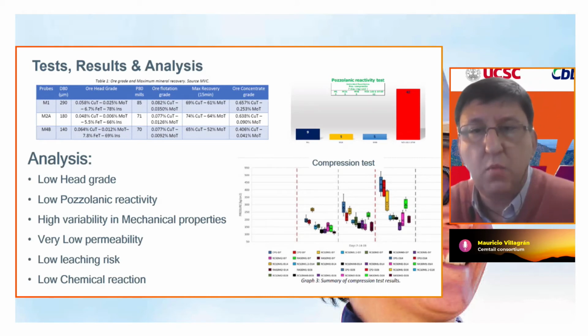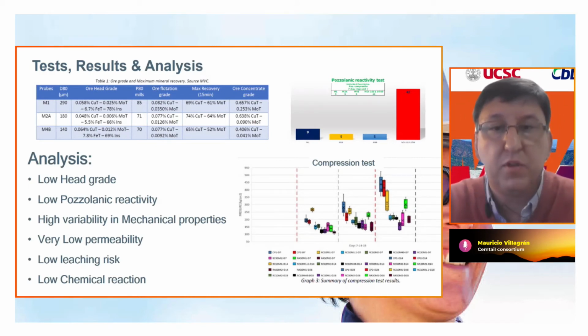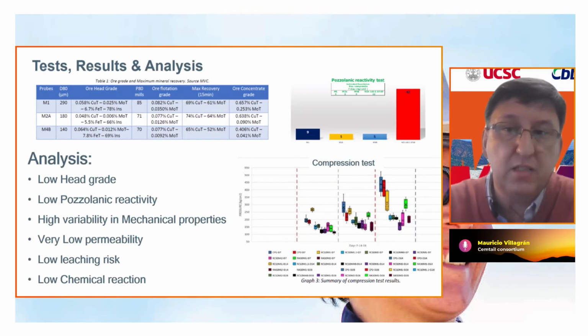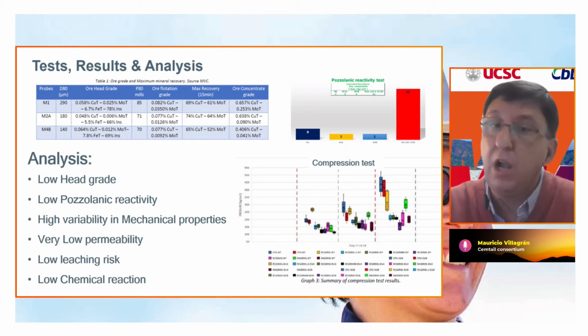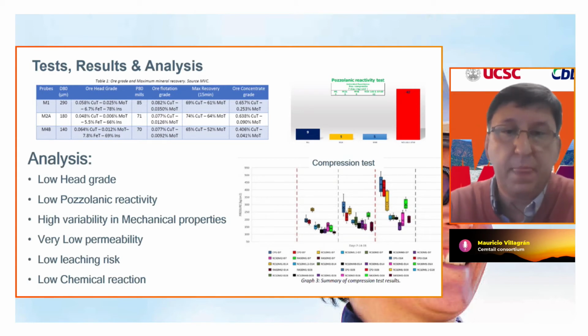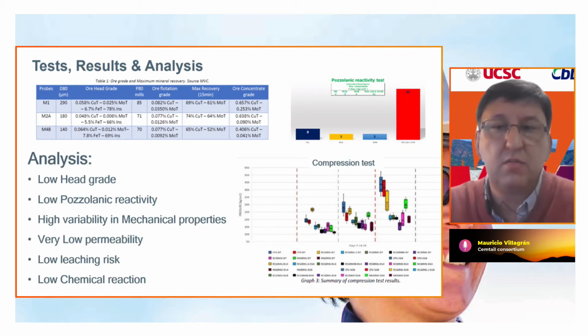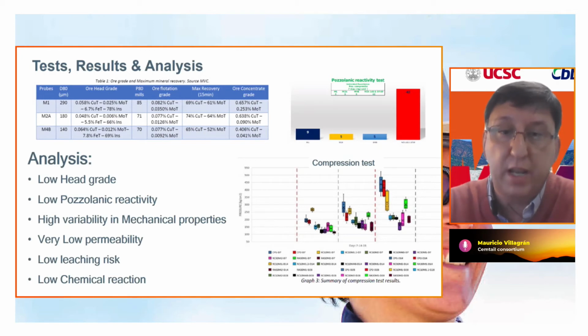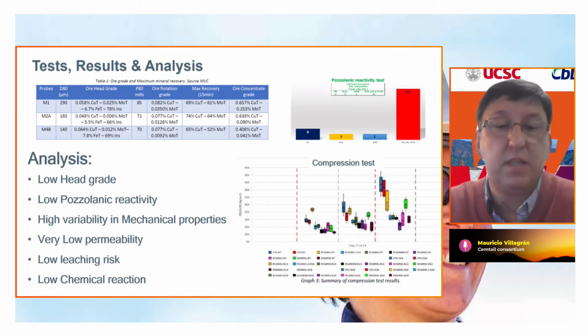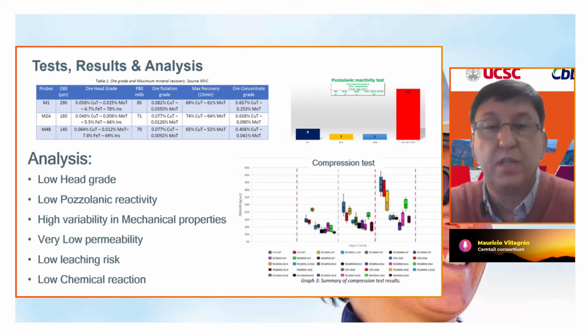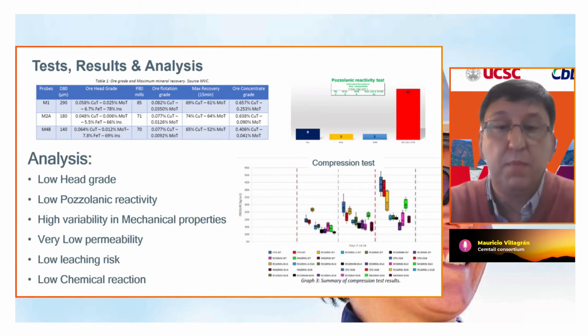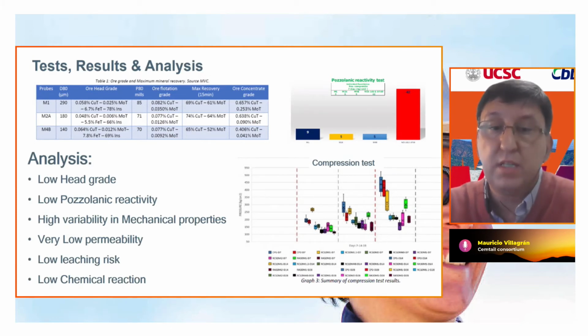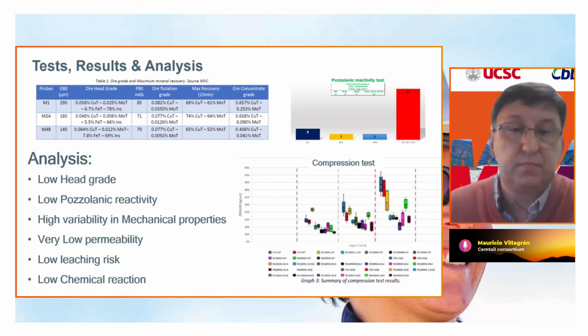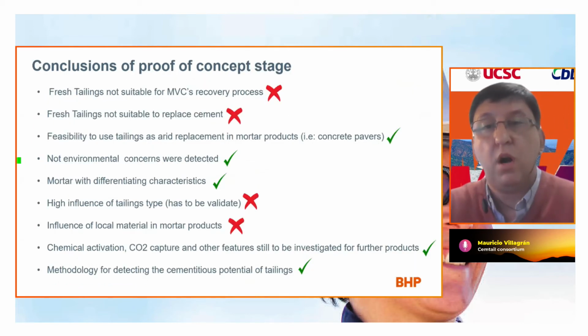Among the most important, we can mention tests to detect the grades of the material, pozzolanic potential of the tailings, mechanical tests of the specimen, mineralogical characterization, leaching potential, permeability test, etc. In general terms, our analysis of results shows low head grades, low pozzolanic reactivity, high variability in mechanical properties, very low permeability in the specimens, low leaching risk, and low chemical reaction. Many of these points were already mentioned in the main achievement slide.